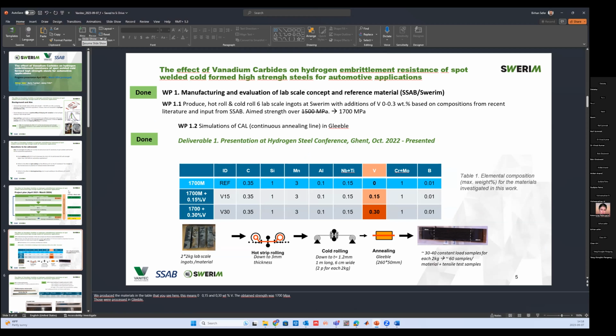We did lab melts of up to 2 kilos with 3 different materials: a reference material that doesn't contain vanadium, and two materials with vanadium levels of 0.15 and 0.30. Then we went through the entire processing, hot rolling, cold rolling, and then we used a Gleeble to simulate the annealing steps.